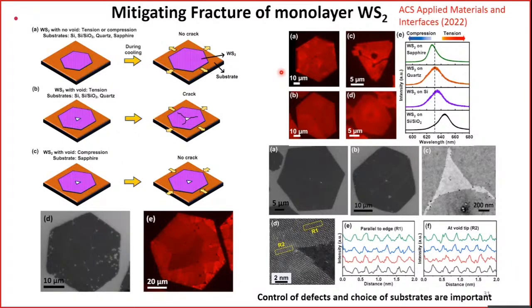Again, we also want to see how we can avoid the cracking. In some cases, we may want to have the voids, we may want to have defects. At the same time, is it possible to avoid the cracking? For that reason, we did a kind of thermal stress engineering by changing the growth substrate. We chose four substrates. WS2 we have grown on sapphire, quartz, silicon, and Si/SiO2. You can see here the arrow marks based on the Raman spectroscopy on the right. The WS2 on sapphire essentially has a compression, whereas WS2 on quartz, silicon, and Si/SiO2, in fact Si/SiO2 is the worst, has a huge amount of tension.